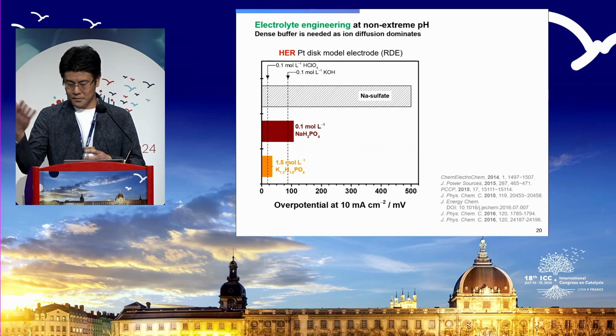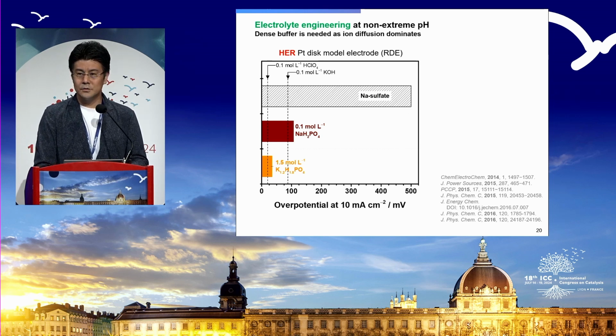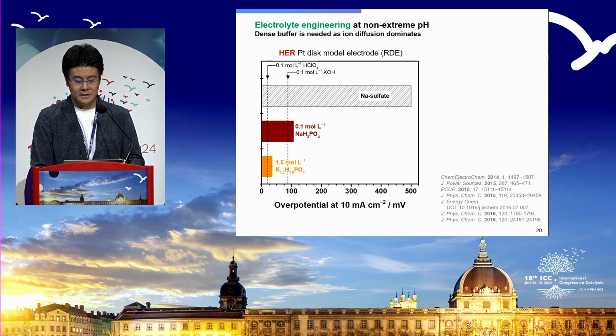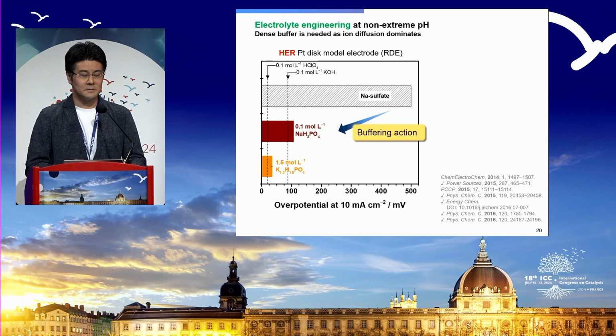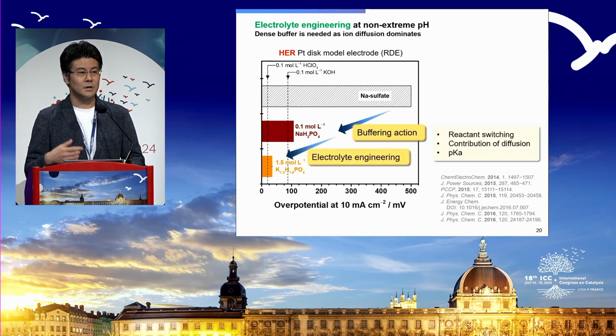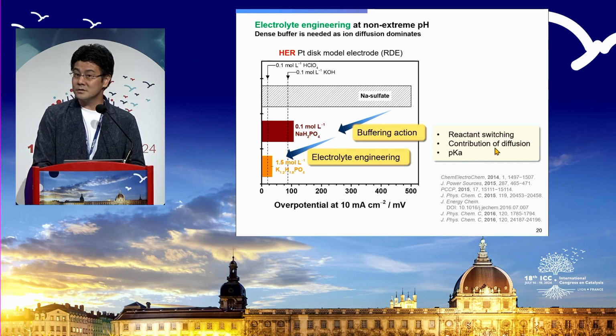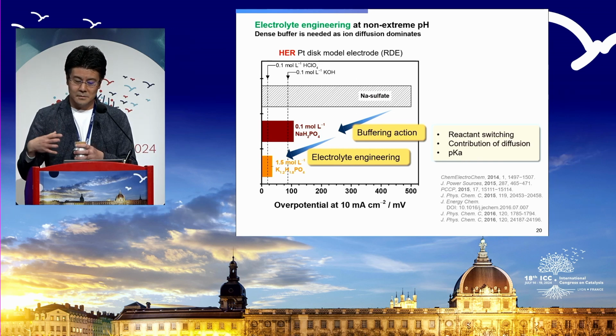To summarize visually, here is what happens in pH 5 or 4 conditions. If you do hydrogen evolution using platinum, you have 500 millivolt overpotential, because it basically shifts the pH and water becomes the reactant. So now you know that buffer should be added. With a little bit of addition, yes, you improve it, but it's not actually enough to supply protons close to the platinum. You need to do what we call electrolyte engineering, to maximize the flux of buffer ions. So here the keywords are reactant switching, contribution of diffusion, and pKa. pKa also certainly helps to minimize this pH gradient.